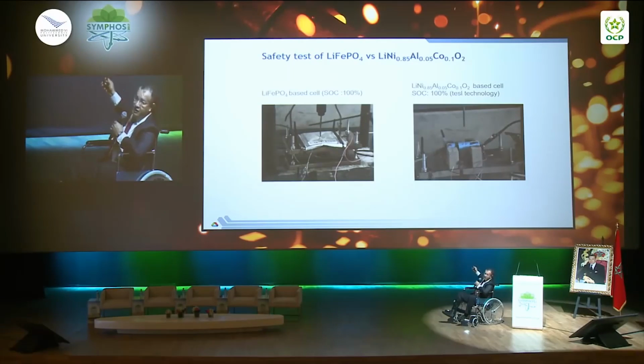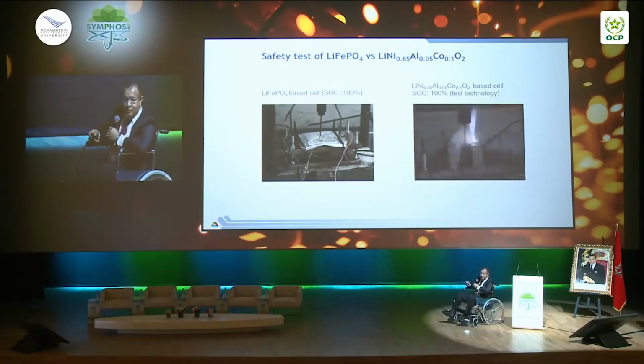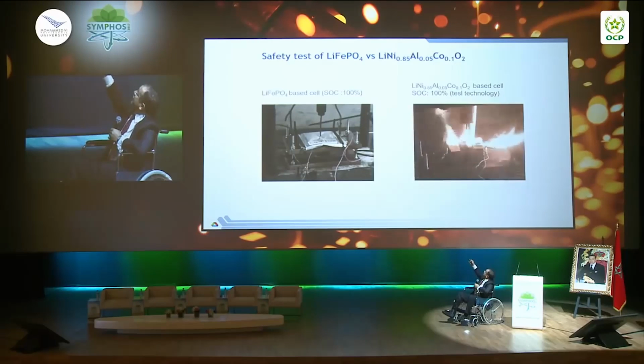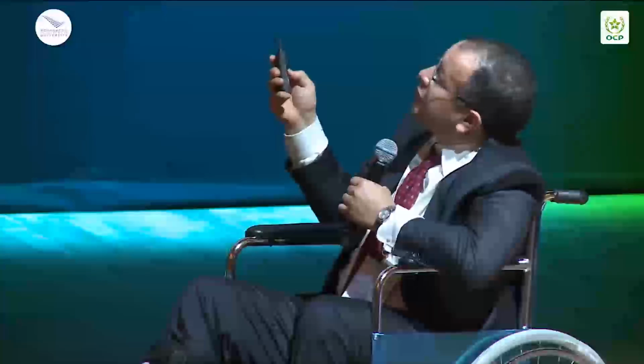This one is using a Tesla Motor Corporation vehicle. So please click on this one. This is what you get. Because this cathode is extremely reactive when you remove lithium. You have nickel 4+, which is unstable in an oxide phase. So you have an immediate decomposition and generation of oxygen that reacts with the electrolyte, which is extremely exothermic. So you end up with a thermal runaway.